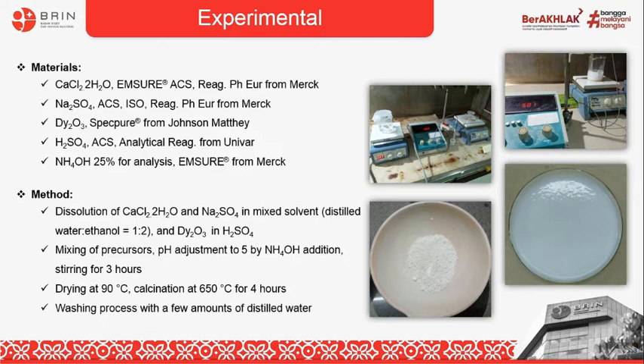The pH value of the mixture was then adjusted to 5 by the addition of ammonia and stirred for 3 hours to obtain a white viscous mixture. The mixture was dried overnight at 90 Celsius degrees and calcined at 650 Celsius degrees in an air atmosphere for 4 hours to obtain the dysprosium calcium sulfate powder. A few rounds of distilled water were used to wash the powder after the heat treatment.